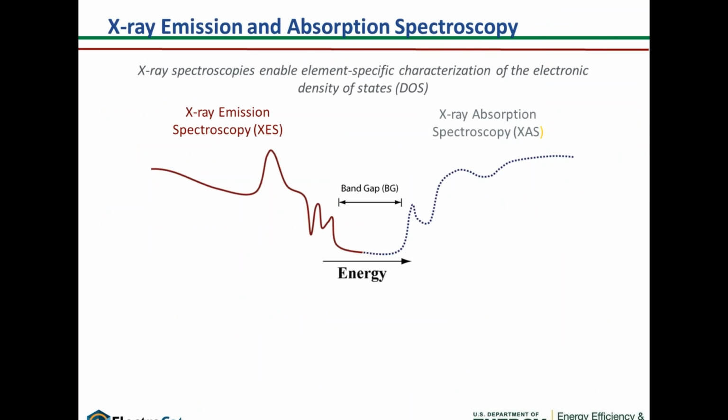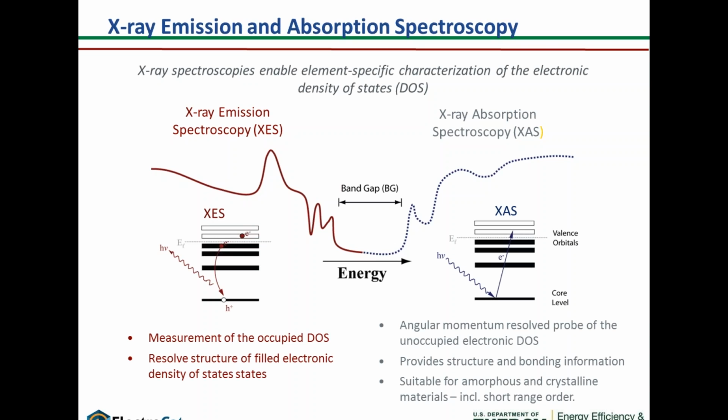At the Advanced Light Source, we have time on 2 different beam lines. One of them gives us access to X-ray emission and absorption spectroscopy. If you could click twice. Thank you. So this is a tool that allows you to either look at the bulk material, if you look at essentially X-ray fluorescence, you integrate the fluorescence, that probes down into the bulk. Alternatively, if you collect total current as a result of being exposed to the soft X-rays, you actually probe the near surface region, like within the first nanometer or 2. So we have access to this. Next slide.